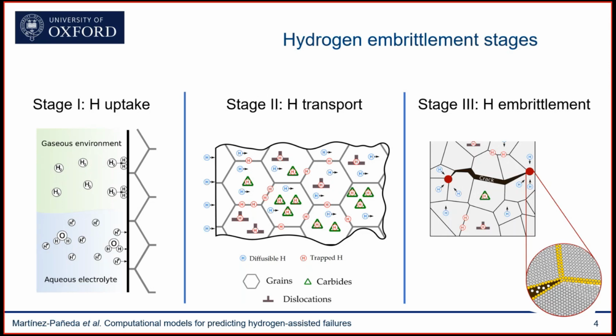So let me walk you through each of the steps involved in the development of our modeling framework. And I will be dividing the work in the three key stages involved in hydrogen embrittlement. One is the uptake of hydrogen into the metal. This is quantifying how much, for a given environment, how much hydrogen enters the metal. The second one is the transport of hydrogen in the metal, so quantifying the diffusion of hydrogen within the crystal structure and its trapping, sequestration at microstructural defects. And then the last one is the embrittlement process itself, the nucleation and growth of cracks due to the accumulation of hydrogen in critical interfaces.